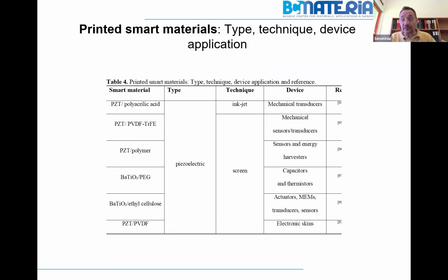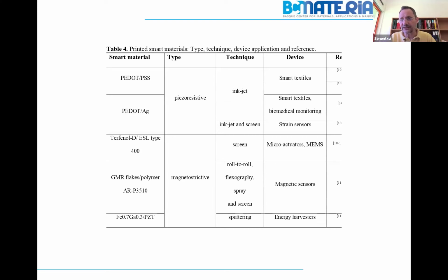And for that, people have been developing a lot of inks, okay? A lot of things, very simple ones, basically dispersing specific particles in specific polymers. As I say, for piezoelectric materials, PZT, barium titanate, in either active or non-active polymers. I say non-active, that only helps the printability, or polymers that also support the specific functional characteristics that I need. For example, PVDF is a piezoelectric polymer. If I put a piezoelectric material in a piezoelectric polymer, probably I have a synergetic effect. Okay? Piezoresistive, variation of the electrical resistance with the deformation, either conductive particles in a conductive polymer or conductive particles in a non-conductive polymer near the percolation threshold. Magnetism, magnetic particles in a non-magnetic polymer, because there are almost no magnetic polymers.